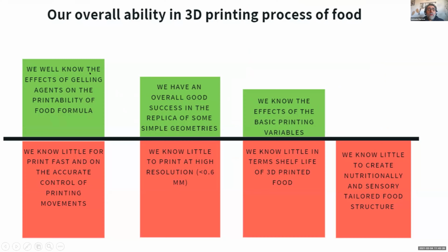What we are able to do and what we need, in green: we know very well the effect of gelling agents to increase printability. We have an overall good success in the replica of some simple geometry, like the previous slide that I showed you. And also we know the effect of the basic printing variables, but we have to add a lot of information for this point. For instance, we don't have information on the possibility to print at high resolution, lower than 0.6 millimeter of nozzle.